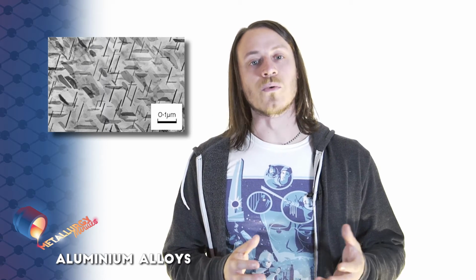To reduce weight further, with a strength penalty paid, of course, we turn to aluminium. In 1903, aluminium was first used in aerospace when it was incorporated into the Wright Brothers' wood frame biplane. Today, 80% of a typical commercial aircraft by weight is made from aluminium alloys. Many of the strongest aluminium alloys, like magnesium alloys, gain their strength from a mechanism called precipitation hardening. This is where blobs of alloying elements clump together within the aluminium. For example, aluminium 2000 series alloys are alloyed with copper, which forms plate precipitates, which contain molecules of 2 aluminium atoms and 1 copper atom within the metal. These precipitates prevent the movement of dislocations, increasing the strength of the metal.